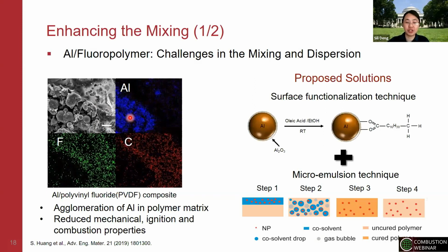So our proposed solution is that we want to bring the techniques developed in materials engineering on surface functionalization, as well as the micro-emulsion technique, to enhance the mixing between aluminum and the fluoropolymers. For example, just to very briefly go through this technique, after the surface functionalization, we can disperse aluminum in, let's say, solvent number 1. And we can dissolve the fluoropolymer in solvent number 2. And then we can mix solvent number 1 and number 2 with the micro-emulsion technique. So in that sense, we are mixing 2 liquids instead of mixing particles into a liquid.